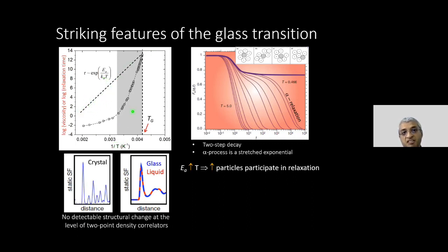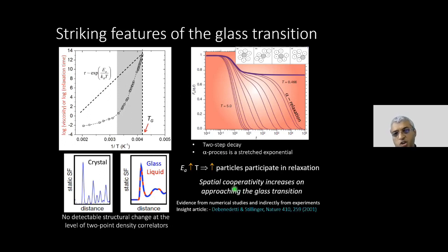The clear deviation from an Arrhenius expression basically tells you that if I were to approach the glass transition, the activation barriers are not the same, but are evolving with cooling. And one way to reconcile both the stretched exponential relaxation and the changing activation barriers is to basically say that more and more particles start participating in a relaxation process. So that's essentially what people mean by saying that as I approach the glass transition, statics is boring, but dynamically I start seeing spatial cooperativity.